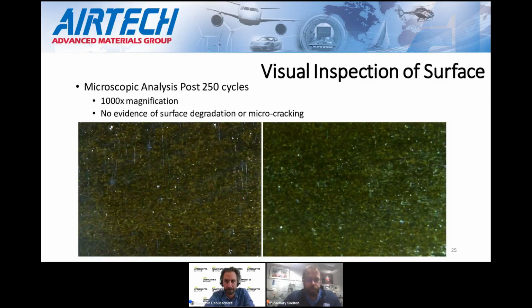Under the microscope, you can see an example of the tool surface. We're not really seeing any evidence of micro cracking or surface degradation. In traditional thermoset systems, the failure mode is typically that micro cracking. That micro cracking leads to delaminations. Ultimately it'll lead to loss of vacuum integrity, but really, we're just seeing no evidence of it whatsoever.